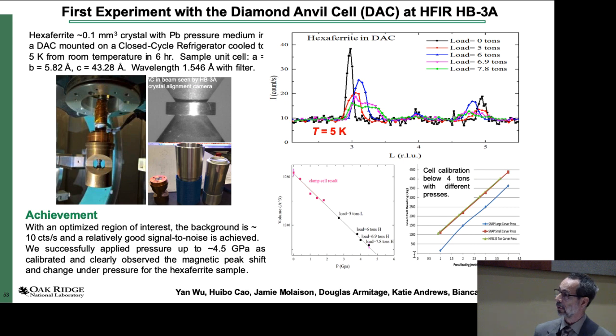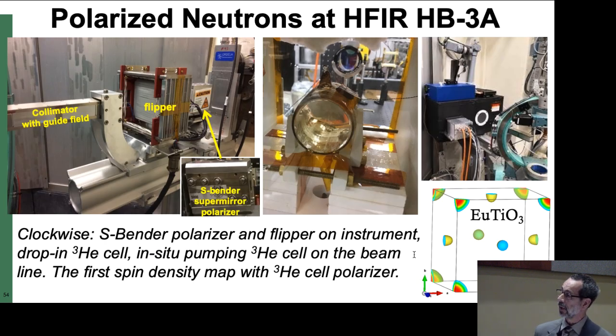As I mentioned, we've been doing high-pressure work. Here's a highlight of diamond anvil cell work led by Yan Wu that has gone up to 4.5 GPa. We've also been doing polarization experiments where we have an S-bender polarizer, also an in situ pumped helium-3 polarizer or drop-in polarizer. These are going to be useful for looking at molecular magnets and magnetization density studies.